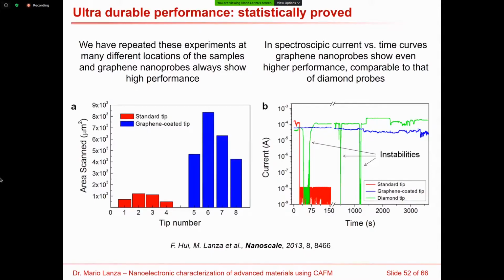And what you can see here is that if we compare the standard tip with the graphene-coated standard tip, the blue and the red lines, you can see that the tip that has graphene shows much longer lifetime. Here, the current densities are so high that they can melt the metallic varnish of the standard tip in just 30 seconds. And for the diamond tip, we see very long lifetime. However, the diamond coating is very rough, and this produces some contact instabilities over time, which is something that we don't have with the metal-coated tips with graphene on top, because these tips are very sharp and the metallic coating is very smooth, as you have seen before in the SEM image.